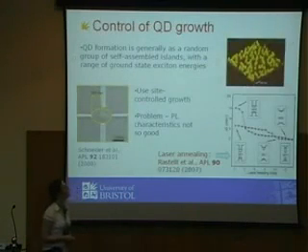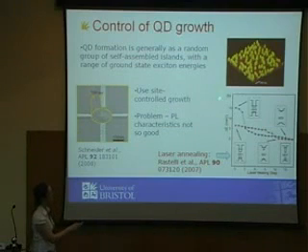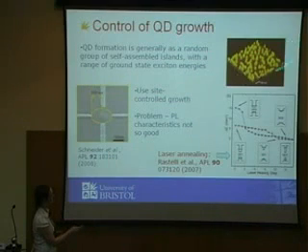So quantum dots then, the ones that we look at, these are self-assembled quantum dots. And self-assembly is a crystal growth technique which produces very high-quality quantum dots. So what you do here, I'm showing you an AFM image of these quantum dots. What we do is deposit indium arsenide slowly onto gallium arsenide. And that allows the formation of these so-called nano islands here.